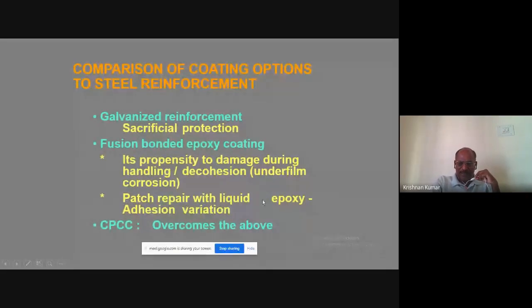So for patch repairing, earlier they used only fusion bonded powders. Then during the repair, people are using epoxy, so that will create an adhesion problem. That is creating more adhesion problem. Because of the adhesion problem, the bond between the coated rod and the concrete is questionable. It has only 0.85 times, but in some other coatings, it has 1.2 times.